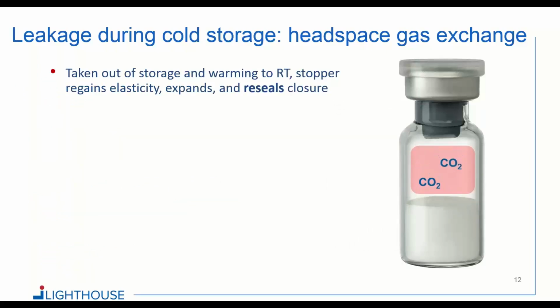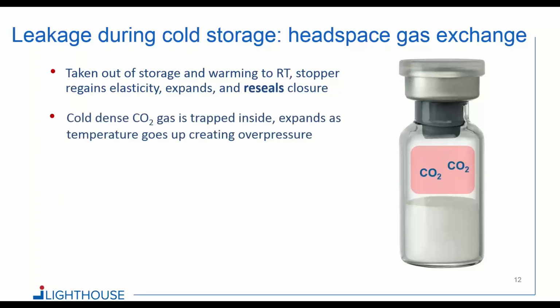Now imagine that you take this vial out of storage and it begins to warm up to room temperature. At a certain temperature, the stopper actually regains its elasticity, expands, and reseals closure. So now the vial is sealed again, but this cold, dense CO2 gas is trapped inside, and as the temperature continues to rise to room temperature, the gas tries to expand and it creates an overpressure.